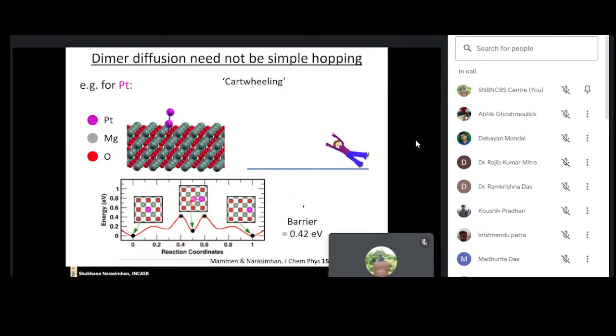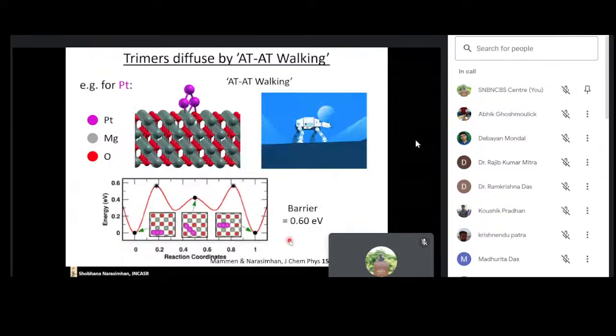Instead, it does this kind of cartwheeling process where the dimer lies flat, then sits vertically, then lies flat and sits vertically. And you see you have a rather more complicated energy profile for this process, and the barrier is much lower. It's 0.42 electron volts. If you have a trimer of platinum, it has a third diffusion mechanism.